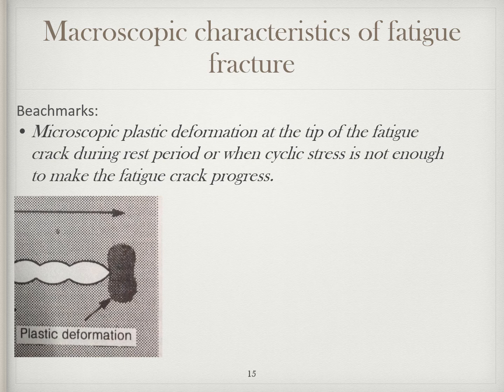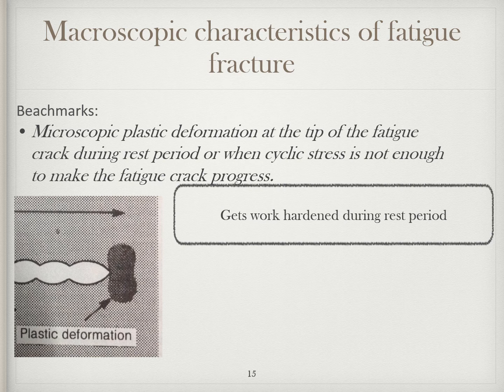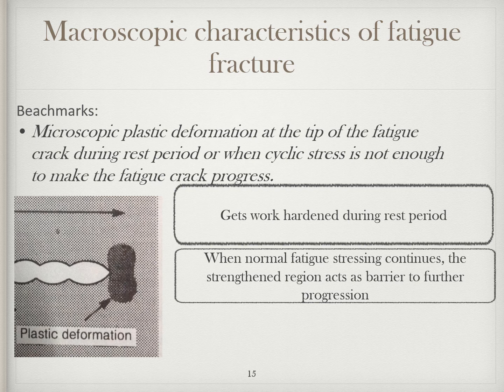At rest for a period of time, this region appears to strengthen by work hardening all along the crack tip. Then, when normal fatigue stressing continues, this strengthened region acts as a temporary barrier to further progression. However, the crack soon breaks through this barrier and the normal fatigue process of striation formation continues. This process results in this barrier or strengthened region appearing as a microscopic ridge or mark on the fractured surface. In effect, it is a giant striation.